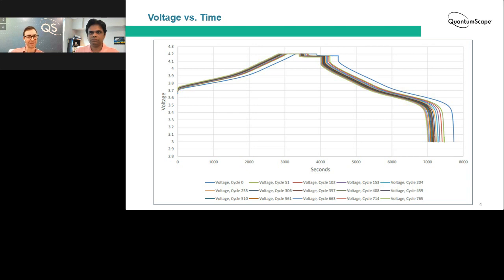And one other point that I'd like to note is why this blue curve is different from the rest. It's because the very first thing before the cycling test that the third-party test lab did was a very slow cycle at C/10, which means a 10-hour charge and discharge. When a 10-hour discharge is done to a battery, it reaches a very low state of charge, and so it can charge up a little bit more. So you'll see that this first charge is a little bit larger than the rest of the charges, but the first discharge is about the same. And so as the curves on the last slide reflected, the discharge capacity is very constant cycle to cycle throughout this test.